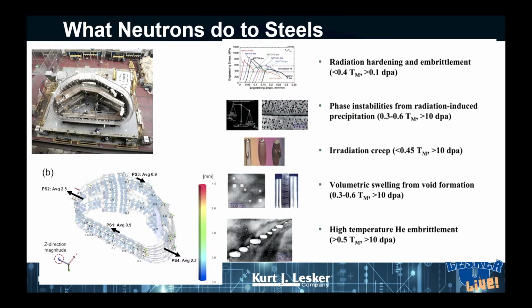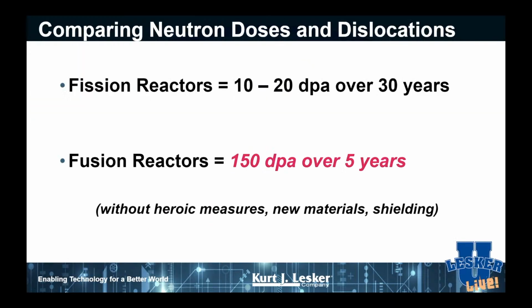And then over time, if you have a really extreme amount of radiation damage there, some of this stuff turns into gases. So now we've got helium pockets and things like that along the grain boundaries of your steel. And so you can imagine things like structural performance, thermal conductivity, all of these wonderful properties that you love about steel start to go to heck. So again, fusion reactors, we love them. They're around for long, long times. You see about 10 displacements per atom over 30 years. Fusions now are happening over 5 years.